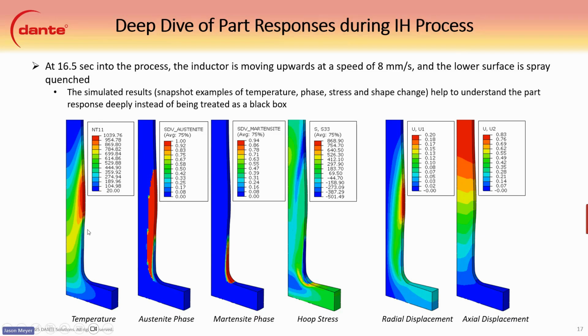And left to right here, we show the temperature. You can see the region that's being heated by the inductor, and you can see that it's being cooled underneath already by the spray quench. We can see the austenite phase being formed from the temperature reaching AC1 here. And you can see that it's not completely uniform down here because some martensite has already begun to form at this time. It is about 94%. It is almost nearly complete right at the surface here. There's still a little bit more to go as it goes up and cools.